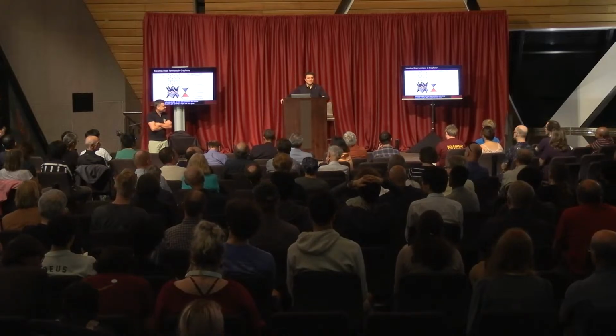Very good question. So maybe I exaggerated a little bit when I said infinitely durable. The question by the lady who asked earlier was about how durable it is, and I interpreted it in terms of electronic properties, when you add charge, which I think was the motivation of the question. In that sense, it's very robust. Graphene is the strongest material in the world when you normalize by size, okay? But still, an individual sheet of graphene, you can tear apart with not too much strength. For example, by making use of the van der Waals interaction, which is relatively weak, but when you take it over a large area, can be a substantial force, and you can tear apart these two pieces of graphene with no problem, okay? The strength of my students doing this, taking that glass slide up, is much stronger than an individual sheet of graphene. So it's no problem at all, actually.